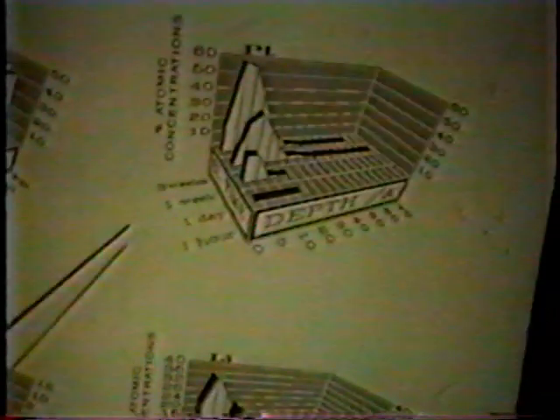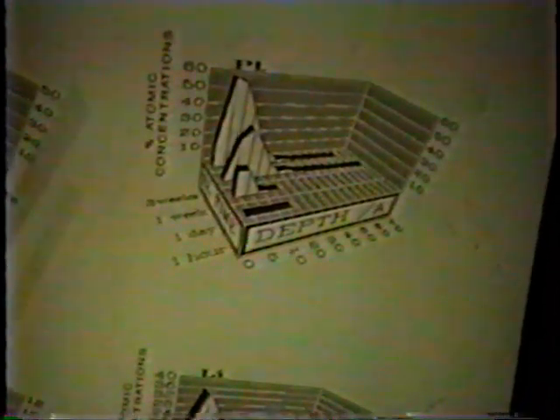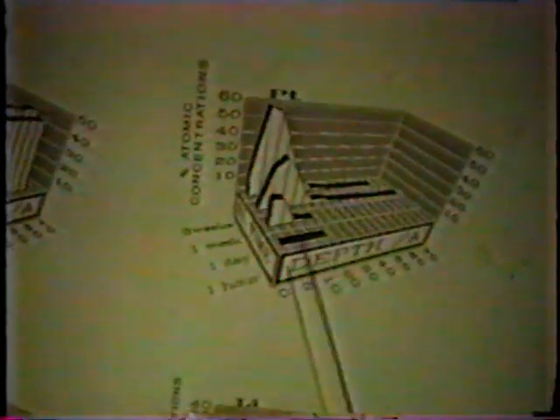Well, now we did our XPS, and we did it at various depths, and here are some quite interesting results which came out of it. Let's just read this graph and show what it means. Concentrate on the platinum, perhaps. Here's 1 hour, 1 day, 1 week, 3 weeks. This is referring to the electrolysis time. This is the examination of the cathode, which has been interrupted after these times here. And this is the depth in angstroms that the angle-resolved XPS result was taken to.